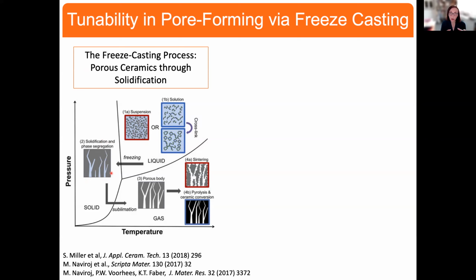So one might produce a mold, take that suspension or solution, pour it into the mold, and that mold is sitting on a cold plate. And so the solvent or the dispersing fluid now begins to freeze. And it freezes in a directional manner, as you see here with these light colored lines. And it's basically pushing either the pre-ceramic polymer or the powders out of the way. And so that is conducted until the solvent is completely frozen. And then we move to lower pressures and sublimate then the